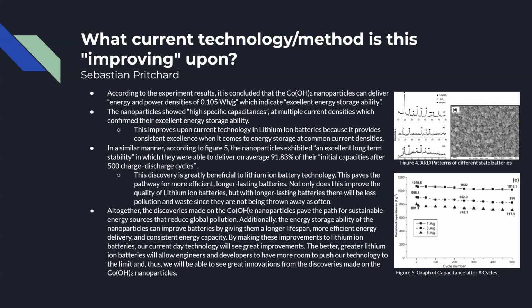In a similar manner, according to Figure 5, as you can see, the nanoparticles exhibited an excellent long-term stability in which they were able to deliver on average 91.83% of their initial capacities after 500 charge and discharge cycles. This discovery is also greatly beneficial to lithium-ion battery technology because this paves the pathway for more efficient, longer-lasting batteries. Not only does this improve the quality of lithium-ion batteries, but with longer-lasting batteries, there will also be less pollution and waste since they are not being thrown away as often.